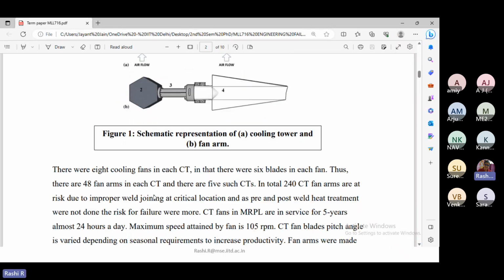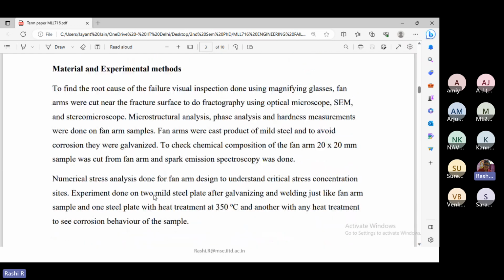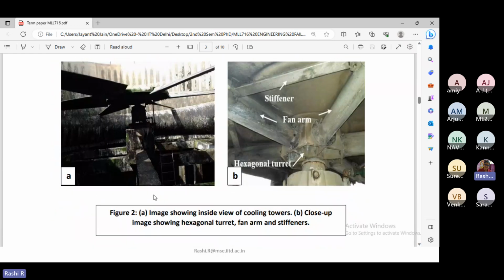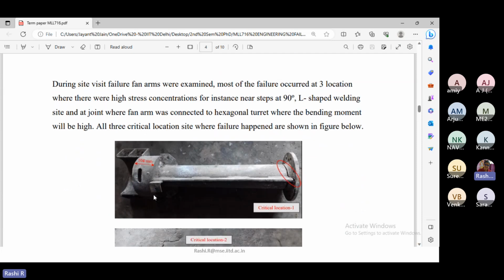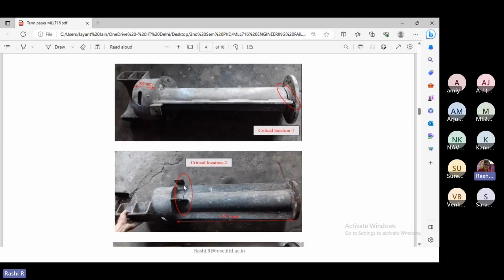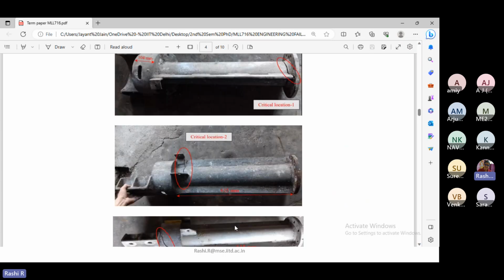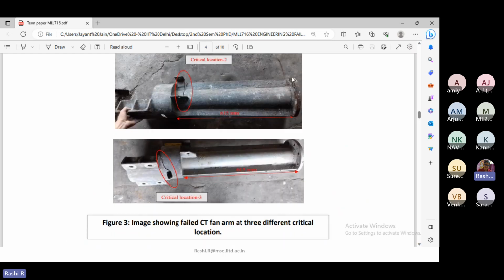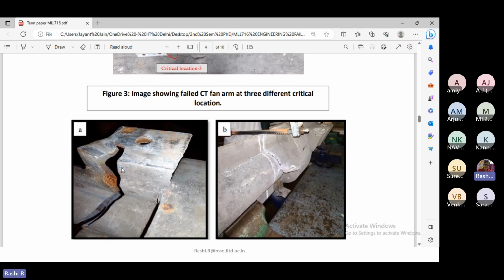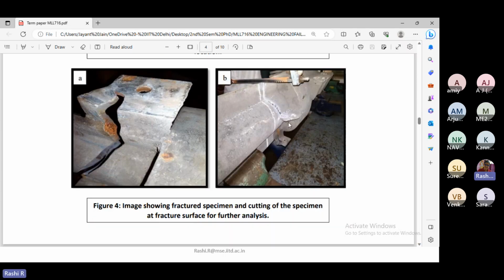So that was a problem that MRPL was suffering, and the analysis showed that most of the cracks were present near the stress concentration regions. When the whole component was drawn using SolidWorks and we saw where the stress concentration regions are, it was present near the weld region as well as near the edges where it is around 90 degrees. And you can see the cracks, how the cracks were present.